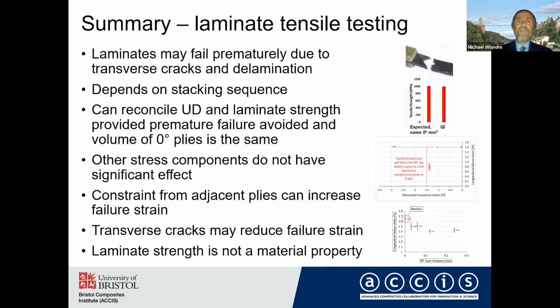So the summary then on the laminate tensile testing: laminates may fail prematurely due to transverse cracks and delamination, and this depends on the stacking sequence and the ply thickness. We can reconcile UD and laminate strength, provided we avoid premature failure, and also provided we take into account the volume of the 0 degree plies. Other stress components do not seem to have a significant effect. This is perhaps a little bit surprising, but on the other hand, when you consider that the tensile failure mechanism is dominated by the strength of the fibers, although the matrix plays a role in transferring load, perhaps it's not so surprising that